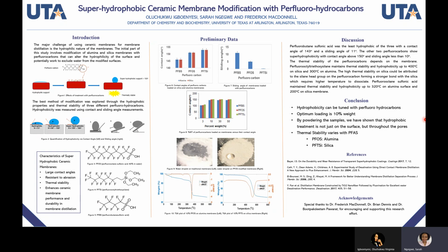In conclusion, hydrophobicity can be tuned with different perfluorohydrocarbons. The optimal loading weight was found to be 10% by weight, and by powdering the samples, we were able to show that the hydrophobic treatment was not just on the surface, but throughout the pores. Also, we would like to note that the thermal stability can also vary with the type of membrane chosen.